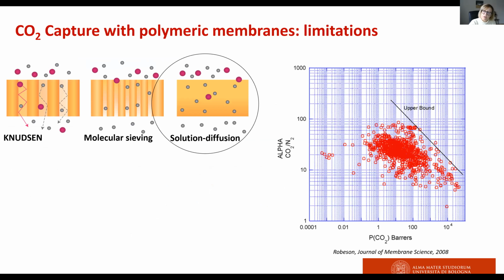What are the limits of polymeric membranes? If the size selective membranes are considered, we can observe an upper bound, which was first reported by Robeson in 1991 and constantly updated with the discovery of new materials. The upper bound basically says that you cannot have a material which simultaneously shows high permeability and high selectivity.